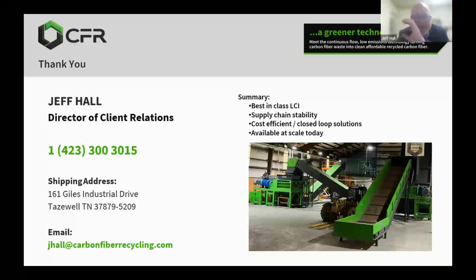That is a fantastic question. So I told you the reasons why we designed it, right? And we know that typically when you compound with carbon fiber, say for example on a twin screw, that fiber is broken down to less than 300 microns, around 300, sometimes less. So we kept that in mind when we were engineering this pellet. And what we're doing right now is we're working with the Polymer Center in Charlotte to do some lab analysis to look at those characteristics. So that information is forthcoming. I would say just stay tuned. But our intent is to develop some best practices for processing the material and a technical data sheet along with some real world empirical data that you can look at to check those performance characteristics.